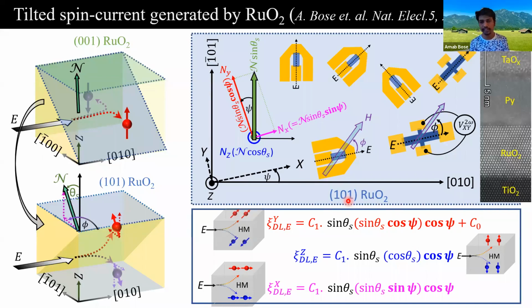There are three important points. First of all, in this sort of materials, it is always important in which direction we run current with respect to crystal axis. Here, theory predicts that it can generate this exotic spin current when we run current along the 0, 1, 0 direction. And it will create zero spin current when we apply in this direction. So it naturally creates cos psi angular dependence because of that. The second point is the generated spins would be parallel to the Néel's vector. So the projection of the Néel's vector comes in the angular expression. For example, for the z component, we have this cos theta. For the y component, we have sin theta cos psi. And for the x component, we'll have sin theta sin psi.